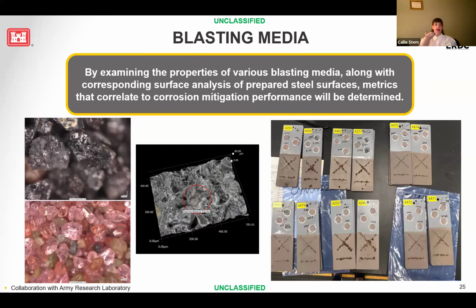On the left here at the very top, you can see some black images. That's just our normal blasting media of aluminum oxide. And then below you see some really pretty pink minerals. These minerals are garnet. If we use garnet and we blast the surface for preparation, we can start to see that these things can be embedded into the surface. This picture in the middle has a circle that says potential material transfer. So what we're seeing is if we use some form of garnet, that garnet is actually going to embed itself into the steel profile.